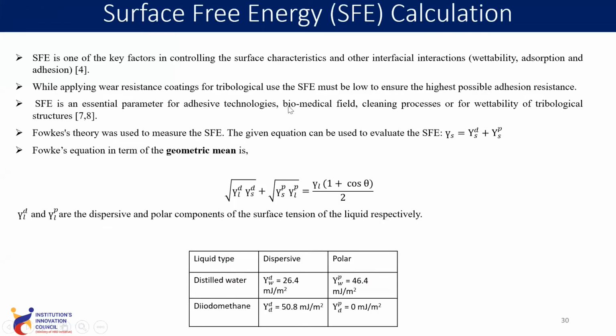Energy calculation. Surface free energy defines the excess energy that a surface has as compared to the bulk. Surface free energy determines biomedical properties, self-cleaning property, and wettability of tribological properties. If the liquid is repelled by the surface, then the surface free energy will be low. It means it will provide the cleaning process in the biomedical component. These are the two liquids that we are using: distilled water and diiodomethane. If the surface energy is large, then it will absorb the liquid; if it is low, it will repel the liquid.